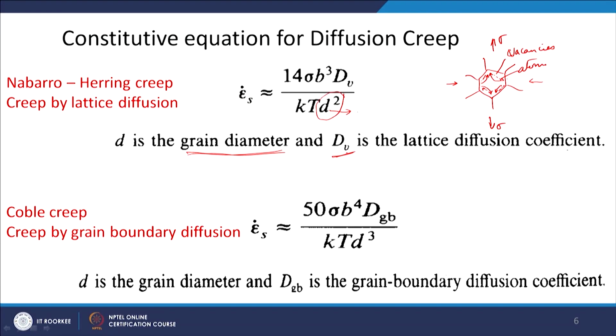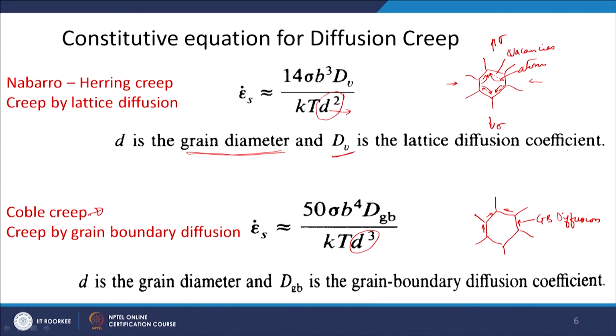Another type, in a similar fashion through a diffusion process, is what we call Coble creep. In this, the creep takes place by grain boundary diffusion. In the earlier case it was through the lattice, and now the diffusion is taking place through the grain boundaries. If I plot a grain like this, the diffusion will take place through the grain boundary here, and because of that there will be an effect on the grain size.